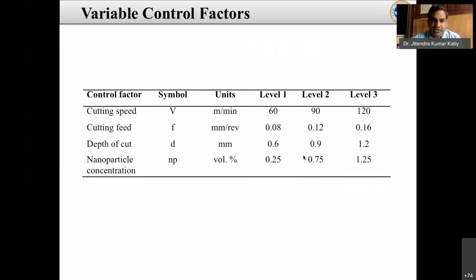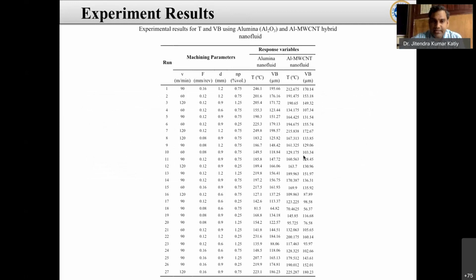So here also we chose 4 parameters at 3 levels. Cutting speed we varied from 60 to 120, then cutting feed, depth of cut, and nanoparticle concentration. And here I have used the RSM method. In that RSM method, we performed 27 experiments, and we obtained the response variables, flank wear and the temperature at the interface. This temperature at the interface we obtained by thermocouples, which we placed using a K-type junction. So a K-type thermocouple is used in this study.